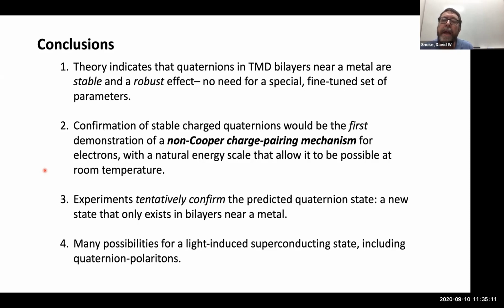The one I would want to do next is one which has a much better binding energy. The binding energy of the exciton here is like 80 to 100 millielectronvolts, and I think you can pick other materials that have several hundred. That makes things simpler in that regard, just because the energies are further separated from each other. But all of these lines, biexcitons, trions, indirect excitons, are generic. It's not something unique to tungsten. It's just that it's been well studied in tungsten, so we know what all these lines are.